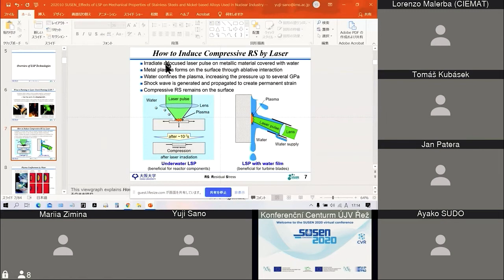If we irradiate a focused laser pulse onto a material covered with water, metal plasma forms on the surface through ablative interaction between the laser pulse and the metal surface. Water confines the plasma, increasing the pressure up to several gigapascals. A shock wave is generated by the high-pressure plasma and propagates inside to create permanent strain. A compressive residual stress remains on the surface after the passage of the shock wave.